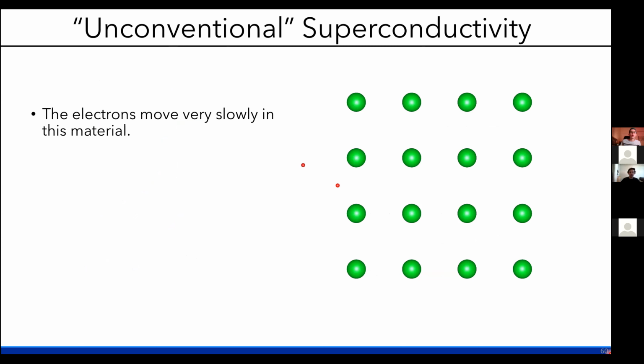And one of the things that makes the superconducting state unusual is that the electrons move very slowly in this material. So the traditional picture of Cooper pairing that I described earlier doesn't really make sense. To illustrate this, I'm going to go back to this highly simplified version for visual clarity. Keep in mind, of course, that what's happening in the real material is a lot more complicated than this. But we see that what happens when the electrons move very slowly is that we initially do get the nuclei that are attracted to this negatively charged electron. But by the time the second electron shows up on the scene, these nuclei have kind of moved back to their original positions. And therefore, these electrons can't pair because there is a lack of this attractive force, and then also there's this repulsion between electrons. So the traditional picture of Cooper pairing doesn't make sense. So there must be something else going on, and we want to figure out what it is.